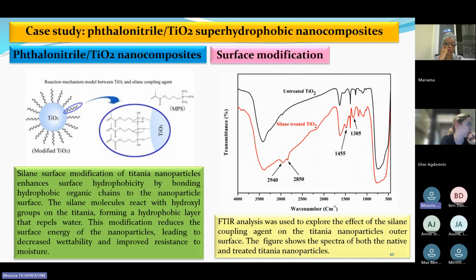The result of the FTIR analysis is displayed in this figure, the right figure. The FTIR was used to explore the effect of the silane coupling agent on the titanium nanoparticles' outer surface. The figure shows the spectra of both the native and treated titanium nanoparticles, and the finding confirmed the grafting of the silane agent on the nanoparticle surfaces.